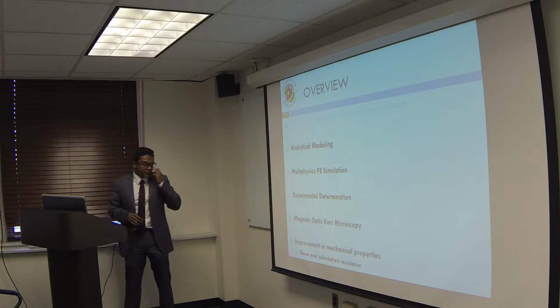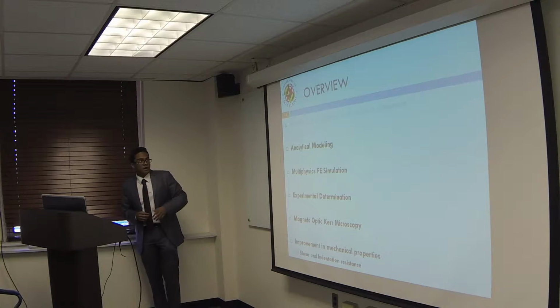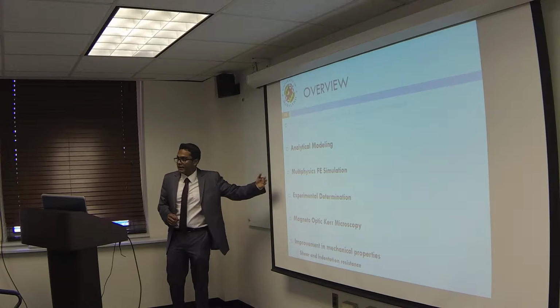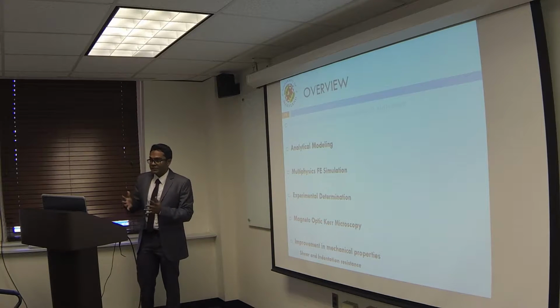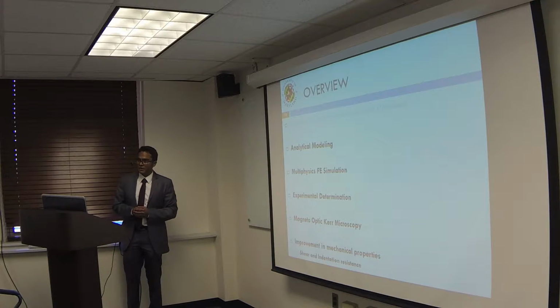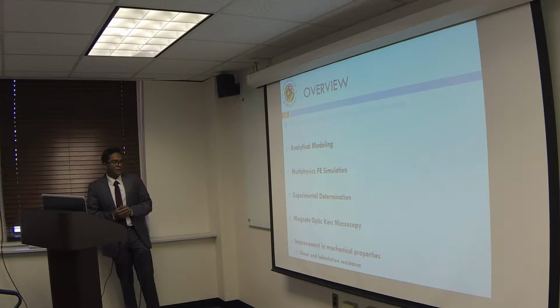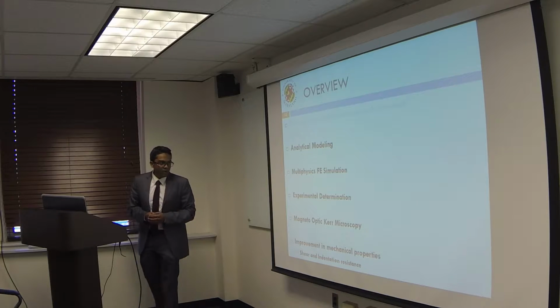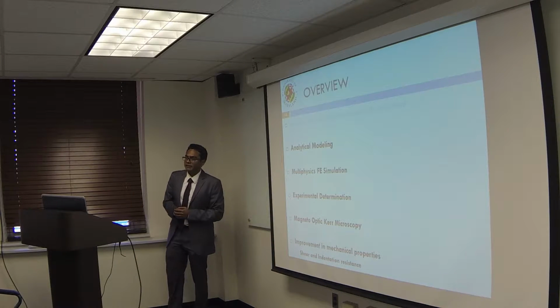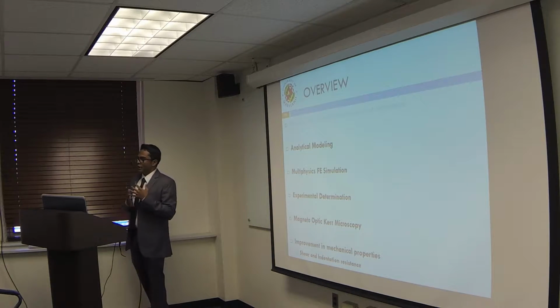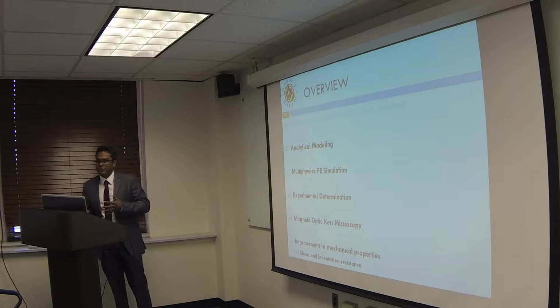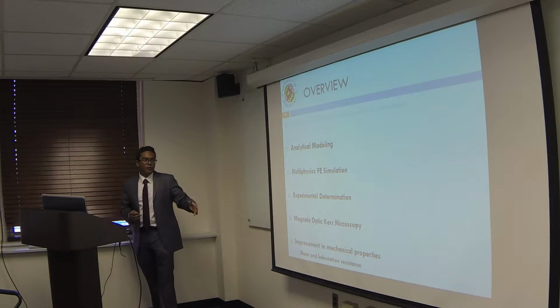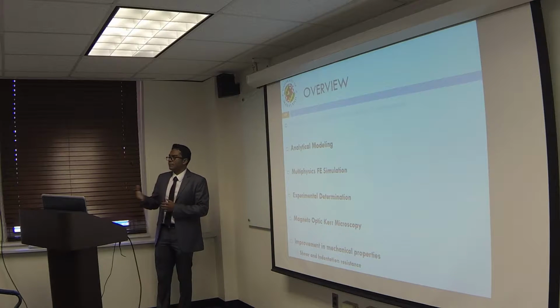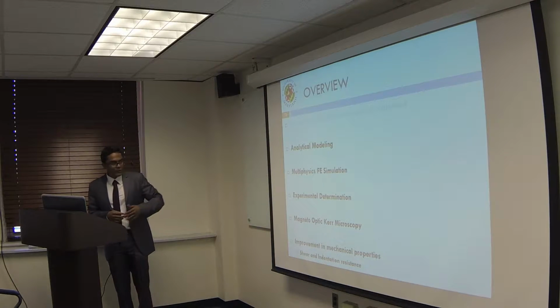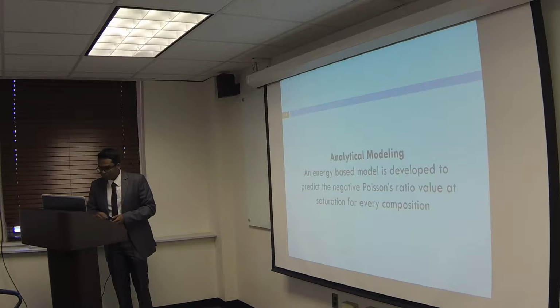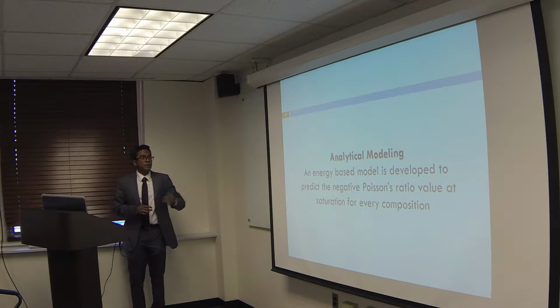To answer these questions, we performed five major tasks in this research. We did some analytical modeling, and we did finite element simulations, multi-physics simulations. We also ran some experiments to characterize this behavior at different compositions. We did some MOKE microscopy, or magneto-optic Kerr effect microscopy, where we would image the magnetic domains and their evolution to understand this behavior. And finally, we wanted to confirm that we were indeed seeing an improvement in the mechanical properties, so we did some indentation testing. First up, we'll start with the analytical modeling.